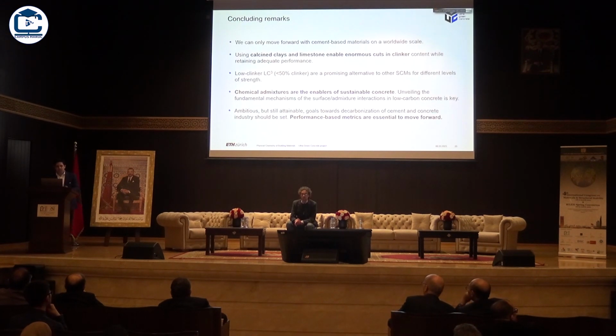So with this, I would like to conclude my presentation with the main ideas that I have presented. First, we can only move forward with cement-based materials on a worldwide scale. There is just nothing else available at scale to make a significant replacement of cement-based material, particularly concrete. Using calcined clays and limestone enables enormous cuts in clinker, not only because they are available, but also because they are reactive. And that reactivity is really what opens this whole new avenue of exploring systems with 20% clinker, 30% clinker, particularly in cases where PC level strength is not required.